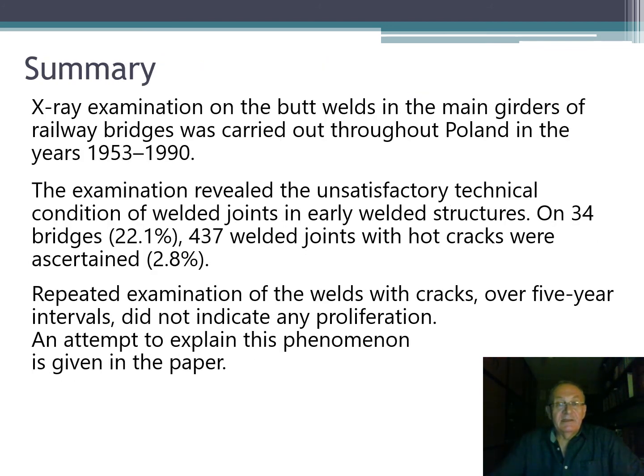In summary, X-ray examination of the butt welds in main girders of railway bridges was carried out throughout Poland in the years 1953-1990. The examination revealed the unsatisfactory technical condition of welded joints in early welded structures. On 34 bridges, this is 22% of them, 437 welded joints with hot cracks were ascertained. This is nearly 3%. Repeated examination of the welds with cracks over 5-year intervals did not indicate any proliferation. An attempt to explain this phenomenon is given in the paper.